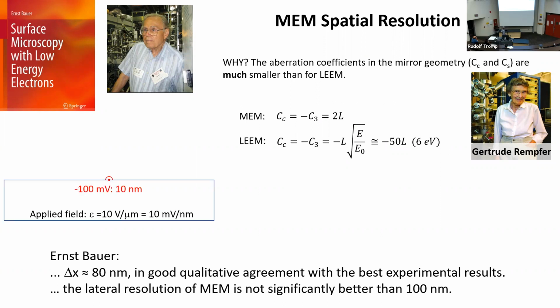Well, it turns out that let's take a sample and let's put a line object on it, right? And let's turn the electrons around at minus 100 millivolts, which means 10 nanometers away from the actual sample, right? So then the equipotential contour due to this line defect looks like this little half circle, right? If you turn around further away, so we make the electrons approach not as closely, you see that circle gets fatter and fatter. So if instead of 100 millivolt away, we turn around 1000 millivolt, then the object has become much fatter, right?